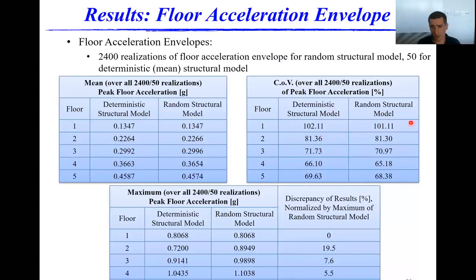One thing I do want to note here, it is kind of interesting, it's a bit counterintuitive that the random structural model actually estimates a lower coefficient of variation than the deterministic case. This is counterintuitive because we're introducing more uncertainty, not less. So you'd expect more uncertainty on the output, but we believe that this might be due to small sample estimation uncertainty with respect to the number of ground motion records that were selected, particularly for the deterministic case. A greater number of ground motion records could very well push the results in the other direction. And also remember that even though these results are very identical to one another, any given ground motion record can still have a lot of sensitivity to the model parameter uncertainty on some floors or some stories.